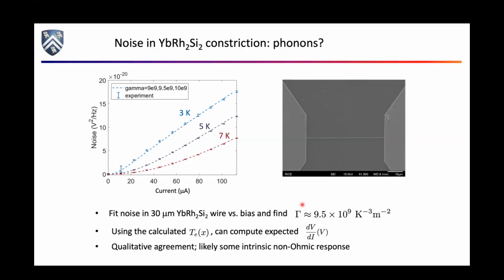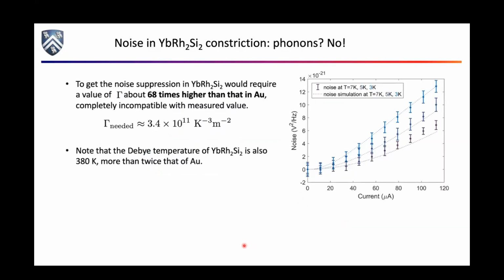When you do this analysis, you find that gamma is a bit bigger than for gold. It's a little less than twice as big as for gold. So, is that enough to explain the noise suppression? No. If you wanted to squish the noise way, way down, gamma would have to be 68 times higher than the value we see in gold, which is just not easy. This is kind of an unphysical number. And the Debye temperature is more than twice what you see in gold. So basically, there's no reason to think phonons are doing anything interesting.